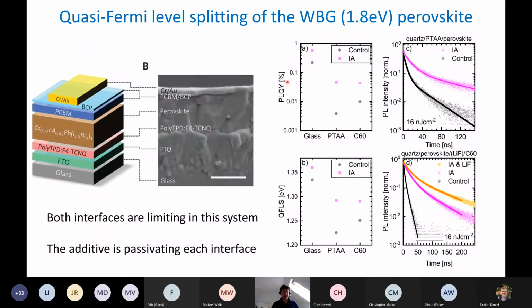of the perovskite absorber. And I mentioned that a perfect solar cell would be 100% emissive. So these are still less than 1% emissive. So they're not perfect by a long way, but this is actually quite good for a solar absorber material. And then from this luminescence efficiency, from understanding the physics and the thermodynamics of what governs the properties of these materials, we can calculate the quasi-Fermi level splitting, which is analogous to voltage in a solar cell. And what we find is these materials should deliver a voltage of about 1.35 volts. In fact, that increases a bit when we add these ionic additives.